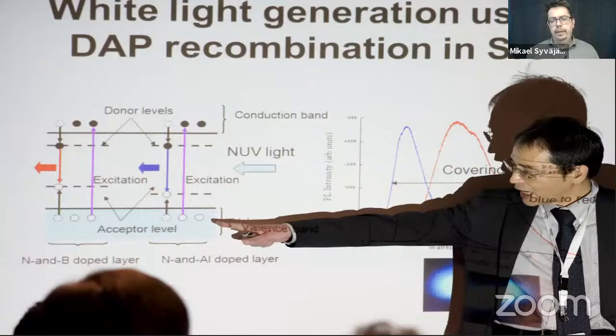So that was some type of milestone. And then a few years later comes Satoshi Kamiyama, who is exploring silicon carbide as LED material. Then you have donors and acceptors, so you can have a recombination between them, and then light comes out from these things. And then he doesn't need pure layers. He wants to add dopants. So there's light coming out from this silicon carbide, so the material becomes fluorescent. And that is the basis for a new type of white LED based on silicon carbide as an active material.